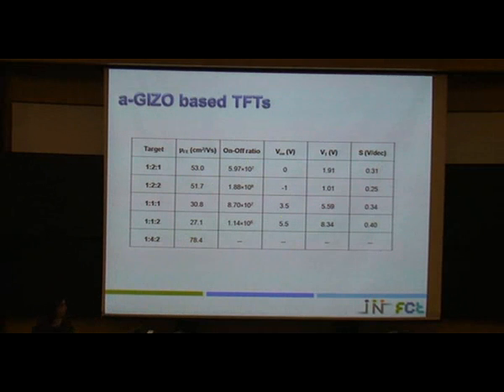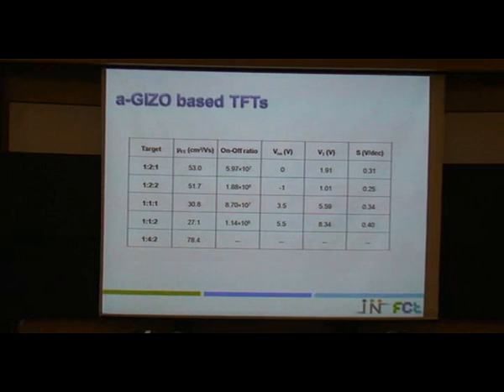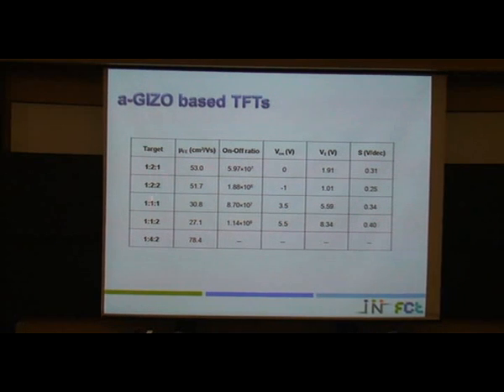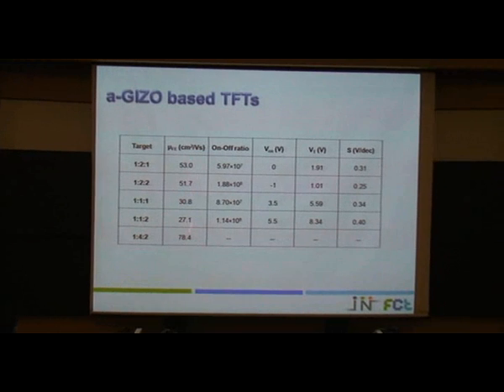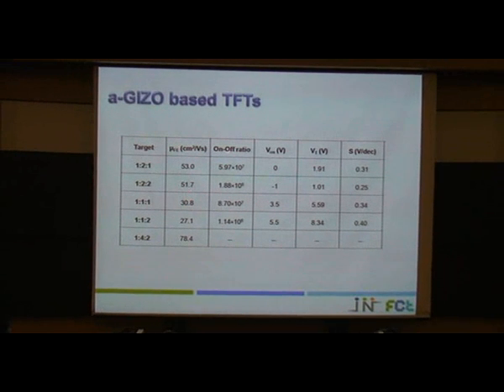Here is a summary of some TFTs that we performed using different compositions, using different targets. What is important for a TFT is the mobility, on-off ratio, the V-on, the threshold voltage, and also the swing voltage, which is important and is associated with the type of interface between the semiconductor and the dielectric layer. But as you see, you can achieve easily mobilities around 50 with a high on-off ratio, a V-on very low, -1 or 0, a threshold voltage around 1, and also a very low swing voltage.